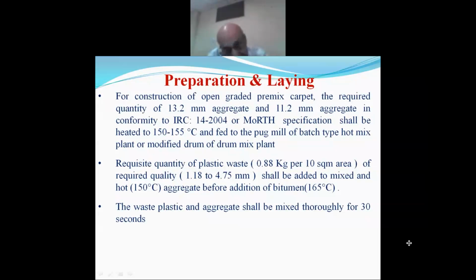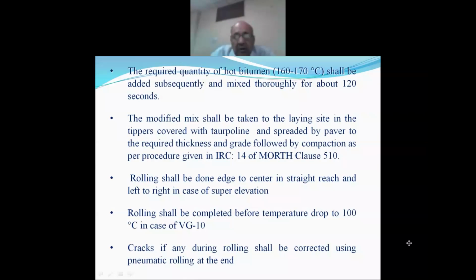For 10 square meter area, the aggregate of nominal size 13.2, passing 22.4 and retained on 11.2 should be 0.18 cubic meter. Coarse aggregate of nominal size 11.2, passing 13.2 and retained on 5.6, 0.09 cubic meter. Bitumen VG10 to VG30. No VG40 grade bitumen is recommended for plastic waste. Bitumen 14.6 kg and plastic waste in 10 square meter area 0.88 kg. So these are the quantities.